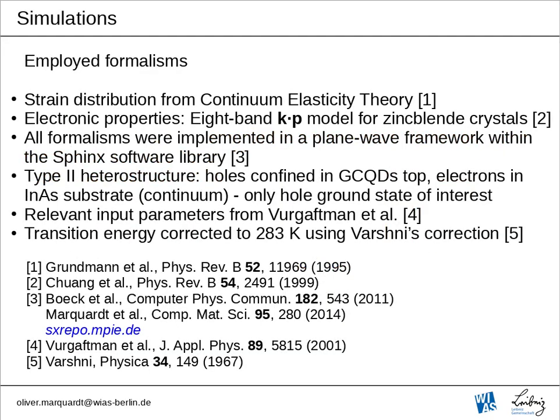We have then performed some simulations to shed more light on the electronic properties of these systems. The formalisms we use here are continuum models. First of all, we have computed the strain distribution using continuum elasticity theory, and this enters, together with many more parameters, the simulation of the electronic properties using an 8-band k.p model for zinc blende crystals. Both formalisms were implemented within the plane wave framework of the S/PHI/nX software library.